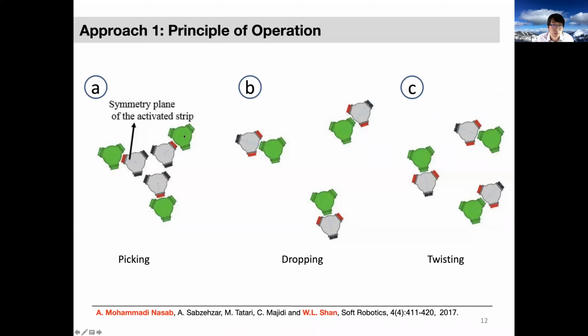The green position, as you can tell in the 3, is the original position, which means you don't do anything. But when you activate this set of ligaments on the outside wall, and then you inflate the 3 fingers, each finger is going to bend inwards, and collectively they can generate this pinching motion. You can also activate the other 2 ligaments on each of the fingers, and then you can generate this opening, and thus you can generate dropping